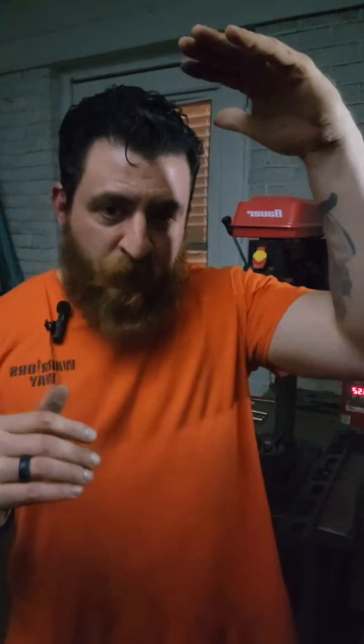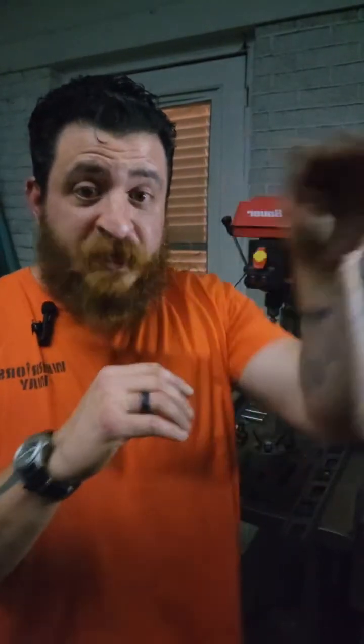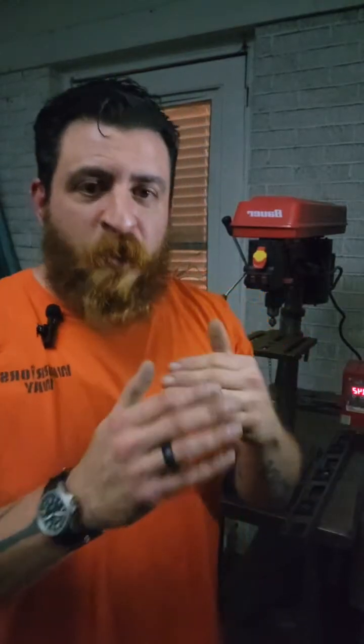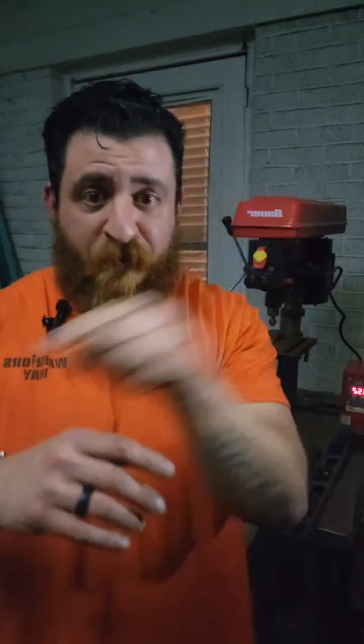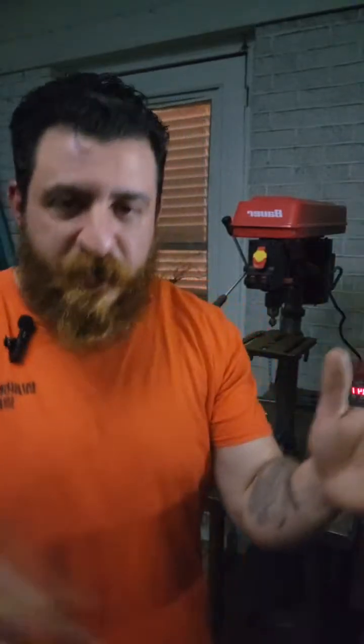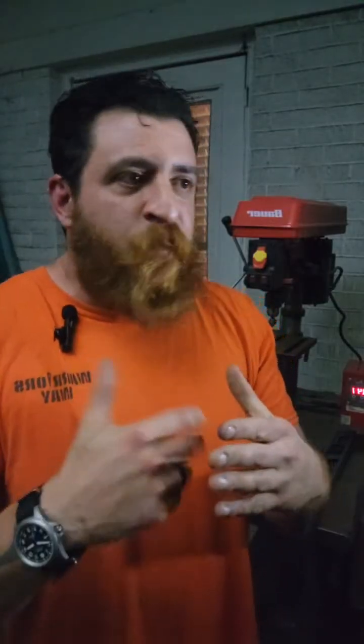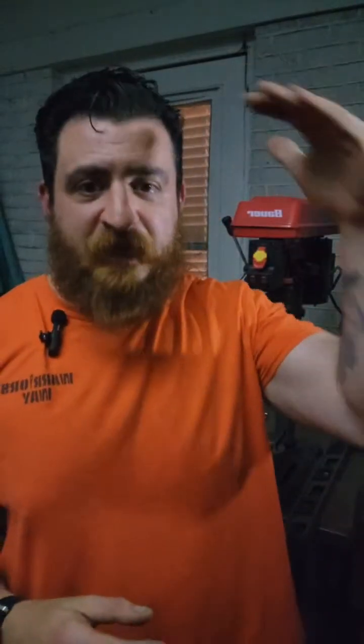Whether I pulled that heat out in 30 seconds or in 3 seconds, there's a curve of diminishing returns. So whether I do it in 3 seconds, 30 seconds, or probably 90 seconds, isn't going to make a difference on the final hardness. It's only as fast as it can go. Whatever the curve is, it could be 2 minutes, it could be 5 minutes, depending on the steel. Every steel has a TTT curve, a curve of how fast it has to cool. Most air hardening steels are somewhere in the ballpark of 10 minutes. Now, 10 minutes versus 1 minute, you're going to get a difference. But once you get under that 2 minute mark, whether it's 2 minutes or 2 seconds, the steel is going to get as hard as it can get. The austenitizing temp really is what dictates it.